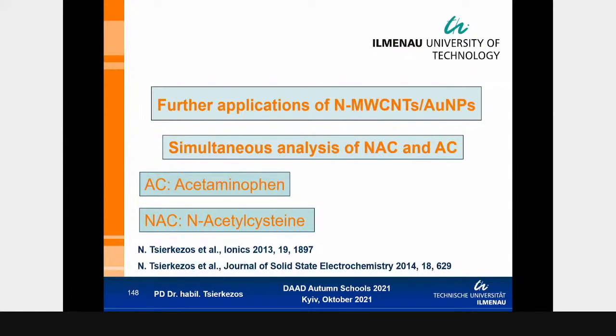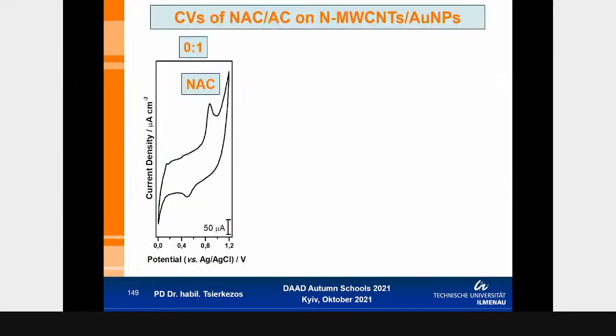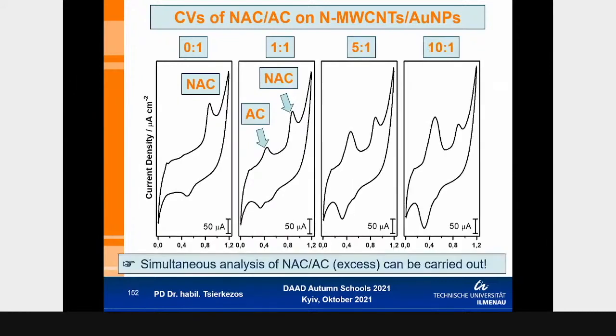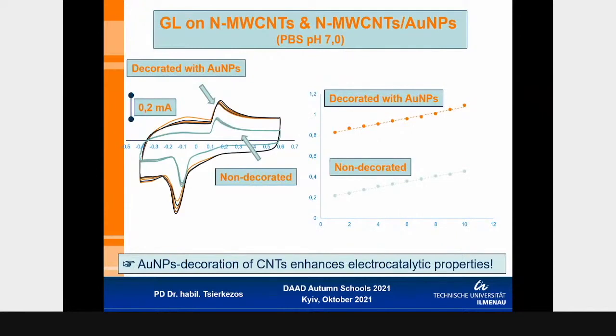Further applications are acetaminophen, which is the paracetamol, in the presence of N-acetylcysteine. Both have been measured, and we observe separated peaks, which are well separated, not overlaid, and which means that you can measure them both in a single measurement. It's also important to mention the effect of the decoration with gold nanoparticles on the current. You can see that with the modification with gold nanoparticles, an increase of about 4 times of the Faraday current you can observe. This is a cyclic voltammogram which has been reported on this system for glucose. So this shows the importance of modifying the carbon nanotubes with gold nanoparticles.